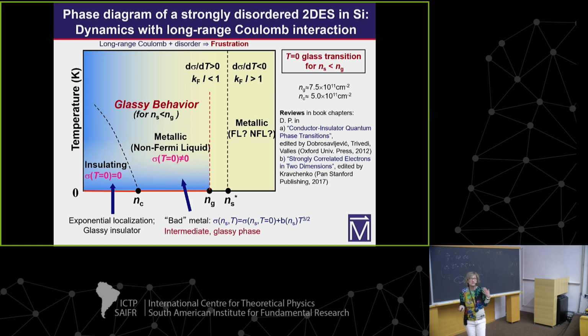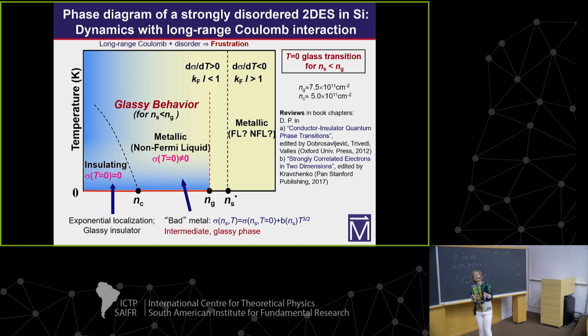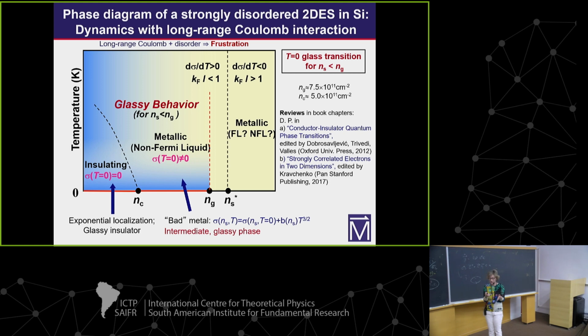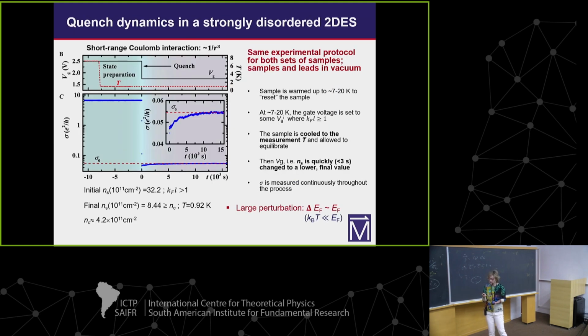Now we want to see what happens when we reduce the range of the Coulomb interaction. For the case of a dipolar interaction, we use the same protocol, exactly the same protocol. We cool the system down to measurement temperature, and then at time equals 0, we perform the quench. We reduce the density to a much lower value. Then we do not change it anymore.